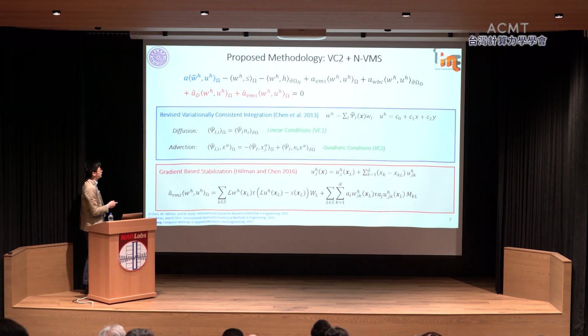And you can use the assumed gradient approach by imposing this residual, the error residual shown here, back into the test function to correct the error. Then you can recover the optimal convergence.